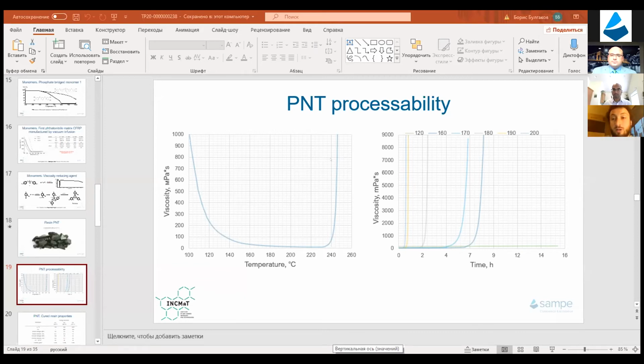All right. Boris, the second question that we have for you is, at what temperature were prepregs produced in your work? Okay, thank you for the question. The prepregs were produced at 120 degrees Celsius. I can show you this. This is a viscosity profile of our resins, and at about 120 degrees Celsius the viscosity is low enough for a good impregnation of the fibers, the fabric, in the case of our prepregs. And it's a convenient temperature for working with the prepreg machine. Higher is not very nice, but 120 is more than affordable.